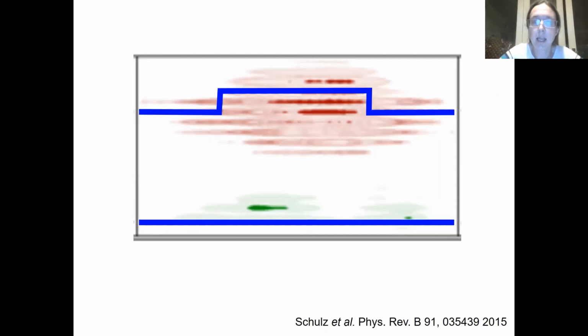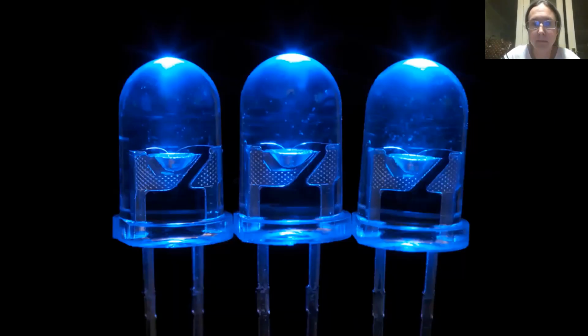Now, what I've got here is a theoretical calculation, a detailed quantum mechanical calculation, which shows where the electron and the hole might actually sit in a structure like this. We can see here that this region where the quantum well is thicker is actually doing quite a good job of trapping the electron. The electron and the hole are trapped separately in these structures, and it actually turns out that the hole may not always be trapped at this well width fluctuation. Sometimes there are just randomly high indium content regions within the quantum well, which might trap the hole themselves. So you don't necessarily always need any particular structure to trap the holes. It's just the fact that there is a random alloy, and sometimes you get a few indium atoms together, provides hole trapping sites.